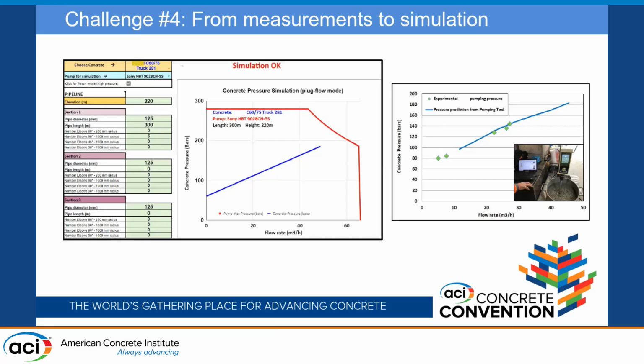That would be essentially 220 up and then a placing boom, so you have some additional resistance. Additionally, we can also put in section 2 and section 3. We can add reducers, we can add rubber pipe. You can do the tribometer test with the rubber coating and take measures of the mix as it hits rubber. With that information, we're able to predict. The blue line is saying, with this particular mix and this particular pump, you see the limitation of it. If you go past that red line, you can't pump it. We could tell the pump operator or the project that with this mix through this pump, you're going to be at almost 200 bar, and you're going to be getting about 45 to 50 cubic meters an hour without doing mock-ups, just doing tribology testing.